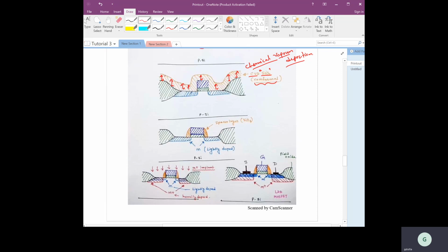See, it will be a time-based etching, to ensure that the etching happens only for this much thickness. After that, the etching will stop. So, time-based etching. Now think about this region. In this region, what is the thickness? This thickness is much higher, right? This thickness is much higher compared to the thickness here or here, right?